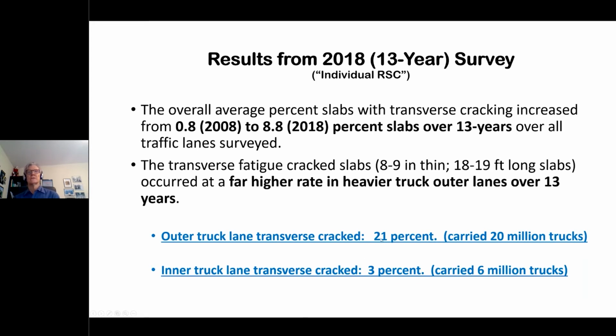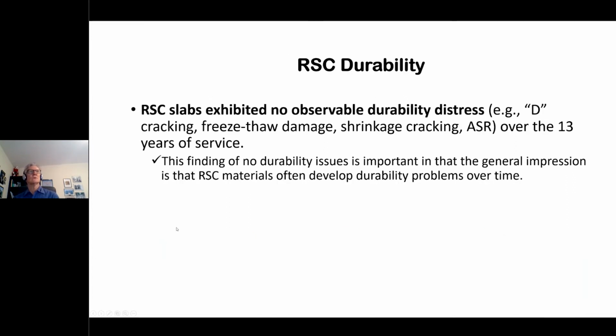So it's obvious it's a fatigue related phenomenon. It's a thin slab, 8 to 9 inches, and long slabs. The predominant cracks were in the 18 to 19 foot sequence of random slab joint spacing. So it's no surprise at all, and it's what one would expect. So that's the structural aspect.